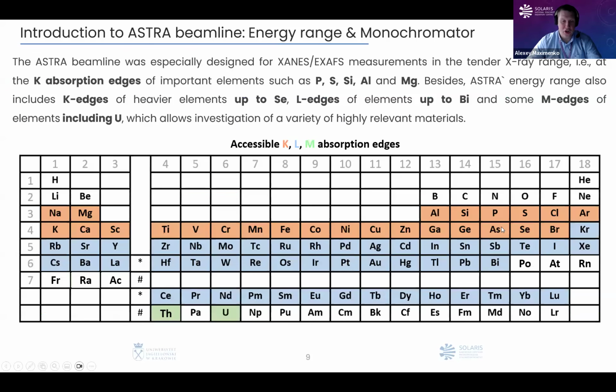Speaking about the energy range in which we are working, from 1 to 15 kiloelectron volts, by changing the crystals which I showed you, we can cover almost the whole periodic table. As you can see, we can measure absorption edges of important elements such as sulfur, chlorine, phosphorus, and also 3D metals such as iron, cobalt, and nickel. If we would like to go for 4D and 5D elements, we can measure L edges of these elements, and for uranium or thorium, we can measure M5 edges.